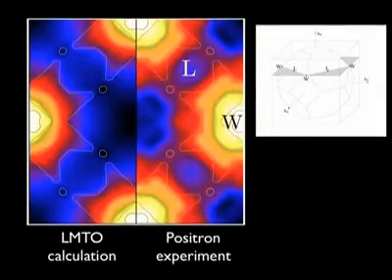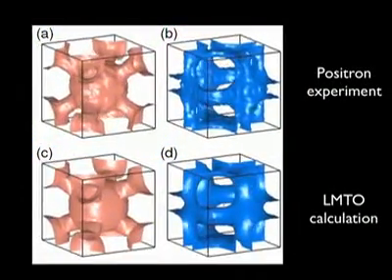Our experiment revealed a Fermi surface topology in excellent agreement with first principles calculations. Specifically, we were able to identify the nesting vector which is associated with the premartensitic transition.